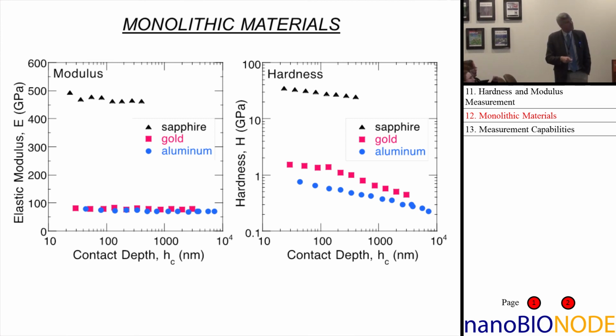So here's modulus, and you can see that for gold, we're getting about 80, aluminum, we're getting about 70. Those are the right numbers within 10% or so, which is about the level of accuracy that you can expect. For sapphire, the modulus is 440 or 400 or something or other, depending. It's anisotropic, so it depends on what direction you want to consider. But you're getting about the right number.